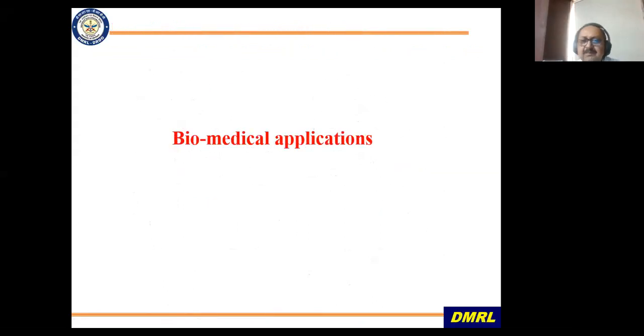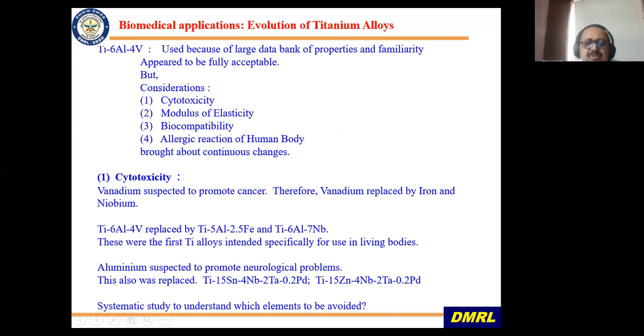So I will just briefly touch upon biomedical and then gamma aluminide and end my talk. Now, titanium alloys, as you know, are very biocompatible. One of the first alloys to be used for biomedical application is Ti6Al4V. Although this is not a very good material, still people use it because there was a lot of data available. But there are issues with Ti6Al4V because vanadium is known to promote cancer. So vanadium is getting replaced in the newer generation alloys, and then aluminium also appears to cause neurological problems. So that is why there are newer alloys which have higher amount of beta but lower aluminium or almost no aluminium.